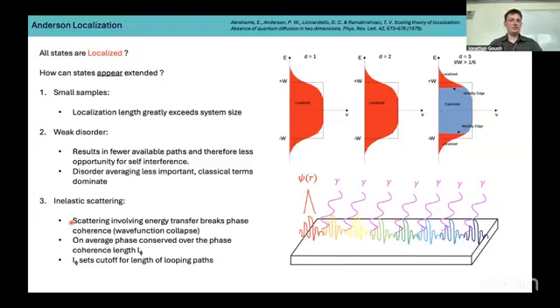So primarily this is due to the lattice, so an electron-phonon interaction, but it can also be due to an electron-electron interaction. So essentially, one way of thinking about this is that due to this transfer of energy between the electron and the environment, you get this wave function collapse, which resets your localization essentially. So you get this scattering rate that's so frequent that you don't observe strong localization.